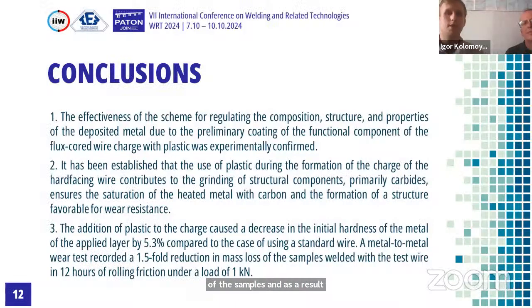And as a conclusion, we can say that the effectiveness of the scheme for regulating the composition, structure, and properties of the deposited metal due to the preliminary coating of the flux-cored wire charge with plastic was experimentally confirmed. It has been established that the use of plastic during the formation of the charge of the hard facing contributes to the grinding of structural components, primarily carbides, ensures the saturation of the heated metal with carbon and the formation of structure favorable for wear resistance.